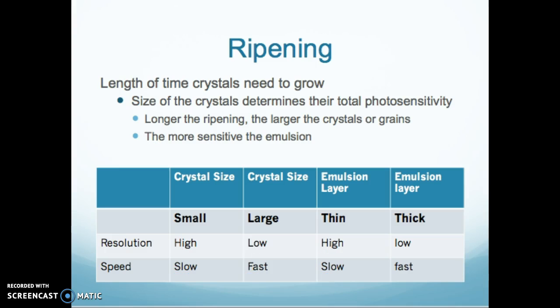Ripening is the length of time the crystals need to grow. The size of the crystal determines their total photosensitivity. The longer the ripening, the larger the crystals or grains, and the more sensitive the emulsion. Looking at the graph here, if the crystal size is small, the resolution is going to be high, and the speed is going to be really slow. As the crystal size gets larger, your resolution is going to drop, but the speed is going to be faster. So you have to understand that as you change your crystal size, the speed of your film is going to change.